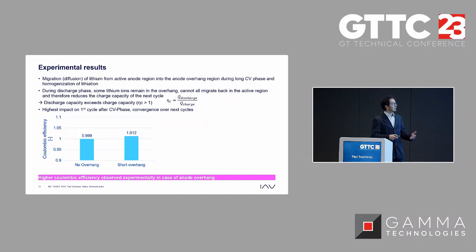That's why if we look at the Coulombic efficiency, we get values higher than 1, so 1.2%, which means that we have demonstrated experimentally that these regions are filled, and then empty in the next cycle, and impact the SOC.